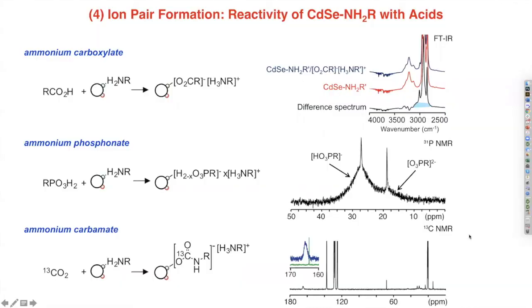Bottles of primary amine accumulate this ammonium carbamate salt on their threads, which is that white crusty powder. And for a sample of particles that only has these primary amine ligands bound, CO2 can dissolve in that solution and form these ion pairs that then coordinate to the particle. And this particular example used carbon labeled, C13 labeled CO2 to demonstrate how adsorption of the C13 label gives rise to this broadening of the coordinated carbamate salt.